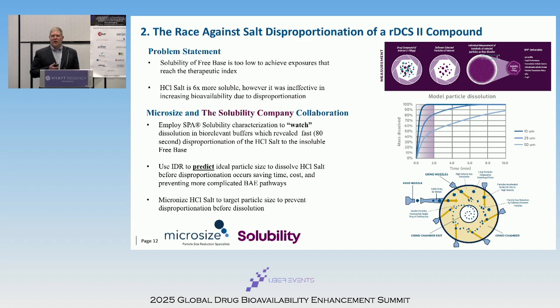The second part is the race against salt disproportionation of a BCS class 2 compound. So there is a poorly soluble, poorly bioavailable freebase. The customer tried to make a salt out of it, which they were successful at. It was 6 times more soluble. However, the bioavailability was not there. It was ineffective just because the material was disproportionating. So what we did was employ the SPA methodology, and we watched the particles dissolve, and we saw a 2-phase dissolution where we're basically able to capture the time where the HCl salt dissolved, but then we saw the lag phase where the material disproportionated.